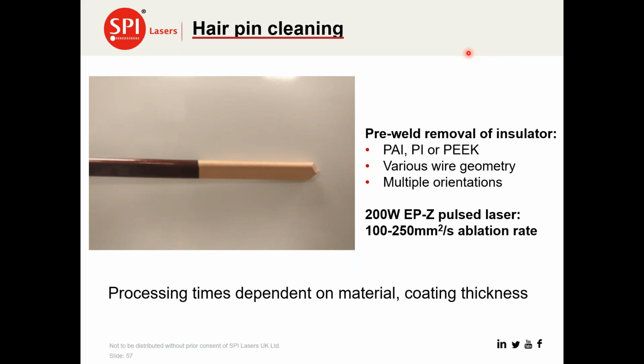Conventionally, these have been either mechanically stripped or stripped using CO2 lasers or other fiber lasers or other disc lasers. The problem with CO2 is residual, getting material right down to the copper. And mechanical, well, it's mechanical. There's a lot of dust generated, and there's wear of the brushes that are used.